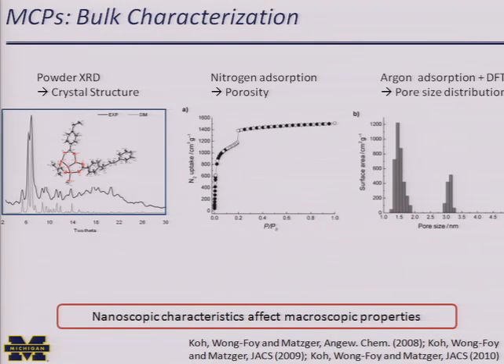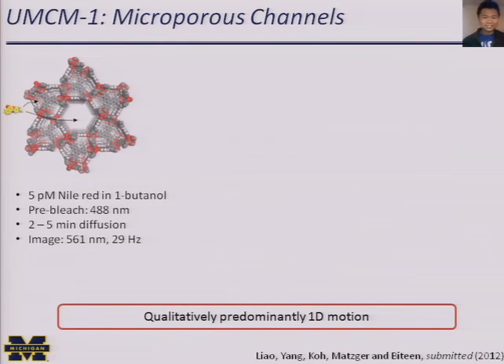And if we're thinking, for example, of catalysis, Callie was showing us gorgeous examples in the side of SIRS, where every little spot is subtly different. And if we think about catalysis, that has to be true as well. So what we did was we imaged Nile red inside of these materials. As W mentioned before, Nile red is very surface sensitive and very environmentally sensitive. So the nice thing with Nile red is we only saw molecules that were inside the crystals and not the others. This work was done by Yi Liao in my group.